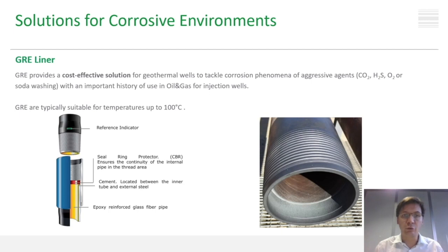In a similar way to internal plastic coating, GRE liner may be a cost-effective solution for geothermal wells. GRE liners are glass-reinforced epoxy liners, which are inserted inside steel pipes and bonded through cement. You can see a sketch of this technology on the left. The steel pipe is basically the outer pipe, while the GRE liner represents the inner pipe. We will have a seal ring to grant coating continuity in the connection area, and the connection will be made up as a standard steel connection.